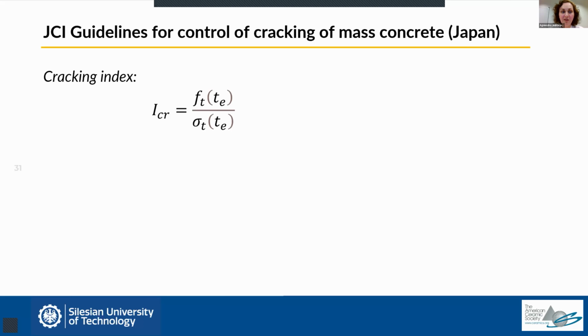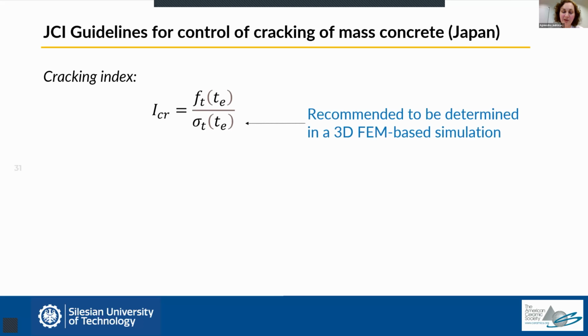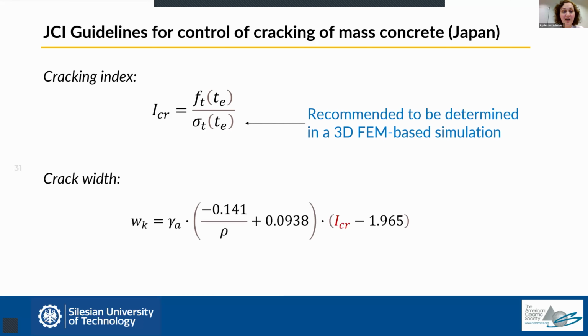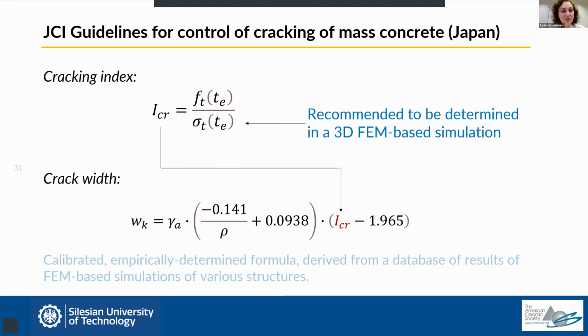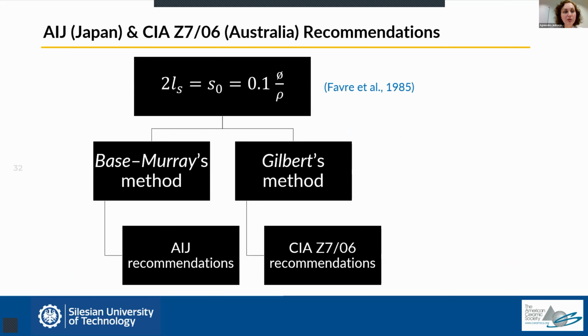which relates tensile strength and tensile stress, but the standard explicitly recommends that this is determined using complex three-dimensional finite-element-based simulations. However, the crack width is then calculated using a fully empirical formula, which uses the cracking index, which was determined this way. And this formula has been developed based on a database of results, which were calculated using finite-element-based simulations. An alternative approach is used both in Japan and in Australia, and they are based on a similar approach, even though they were developed somewhat independently.